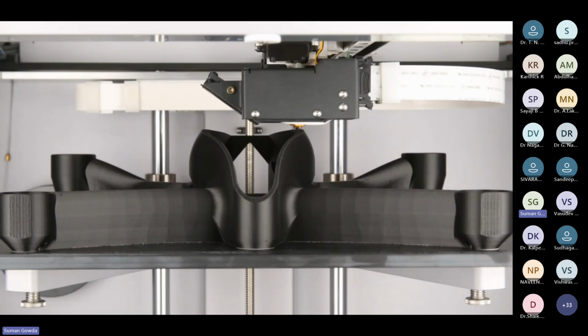And then because of the heat, the fiber gets bonded with the plastic. And then as we build it layer upon layer, the part strength increases by 10 to 20 times. And we always have an option to select the amount of fiber that we are going to deposit. We can deposit fibers which are complete 100% to the part, or we can deposit fibers which are hardly around 10 layers in my 100 layers part. Or if my part is of 100 mm, I can have fibers in the bottom 5 mm and in the top 5 mm. So it completely depends upon me how I want to add the fiber.